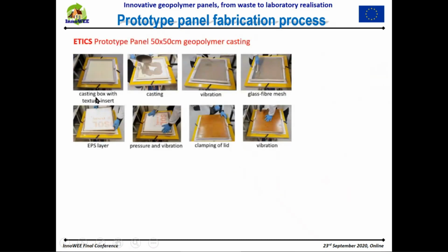For example, for ETICS 50 by 50, the panel was produced with a geopolymer casting in a casting box, where you can also put a texture that gives an aesthetic finish to the panel. Then the box is vibrated because the geopolymer has thixotropic properties and that helps to spread the material.